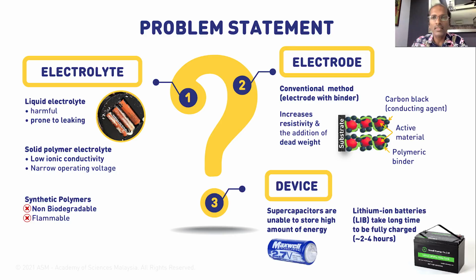The main components of the device are electrolytes and electrodes. For electrolyte, liquid electrolytes are harmful and prone to leaking, whereas solid polymer electrolytes show low ionic conductivity and narrow operating voltage. In addition, the usage of synthetic polymers is non-biodegradable and flammable. For electrode, we can see electrodes with binder increases the resistivity and the addition of dead weight. For devices, supercapacitors are unable to store high amount of energy, whereas lithium-ion batteries take long time to be fully charged, as I've already explained earlier.